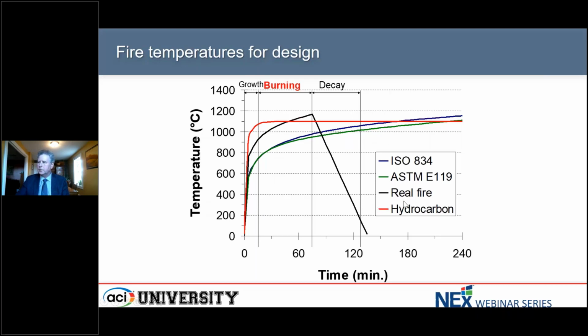But you'll see that there are two other curves that I plotted on here. The red one that is going up very, very steeply, and then has a plateau, that's a hydrocarbon fire, which is quite often used if you're doing designs, say, for a tunnel where you might expect the tanker to be burning. But this black curve that I've shown here, where the temperatures increase to a point and then drop off, that's what we actually expect in a real fire.